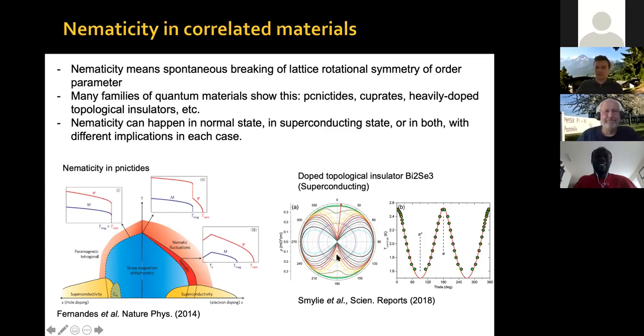An ellipse or a peanut has one axis of symmetry. That means that the system has chosen a direction, okay? Before, the natural rotational symmetry of the crystal is threefold. It's a hexagonal system, and the system chooses a given direction. Some order parameter chooses a given direction, and therefore it exhibits C2 symmetry, an ellipse or a peanut, okay? So this is what the evidence for nematicity is, for example, in this system.